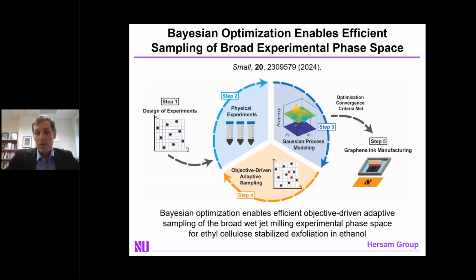And what we've been doing in our lab is trying to utilize the wet jet milling method with different solvents that are more sustainable, such as bio-derived ethanol. This requires also the addition of stabilizing polymers, also bio-derived, such as ethyl cellulose. And in order to optimize the conditions of the wet jet milling, we use Bayesian optimization, which is a machine learning methodology that allows you to very efficiently explore complex and many variable experimental phase spaces.